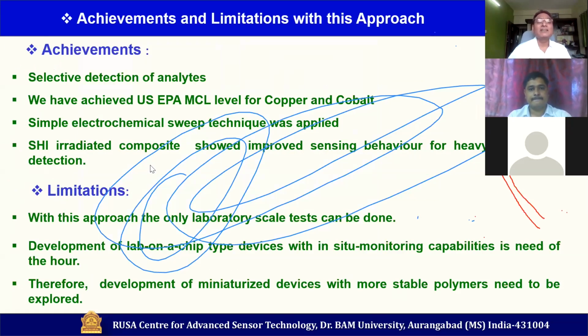So with this result, what was our achievement? Our achievement was we could selectively detect analytes. We have achieved the US EPA level for at least 2 analytes, heavy metals copper and cobalt. We could not reach the MCL level for others. A simple electrochemical sweep technique was applied here, and SHI irradiation also gave us a substantial impact.